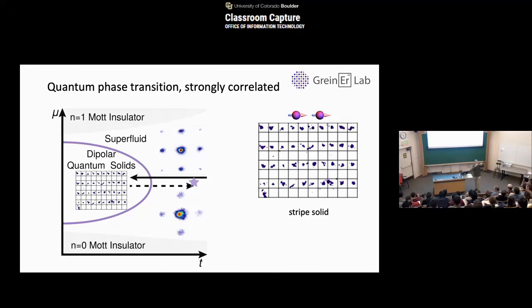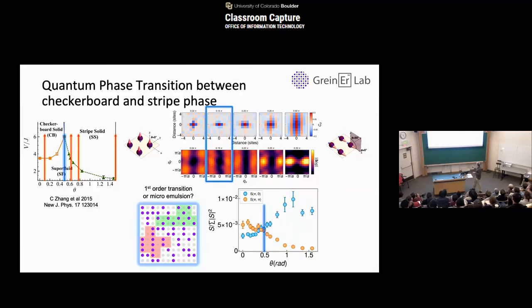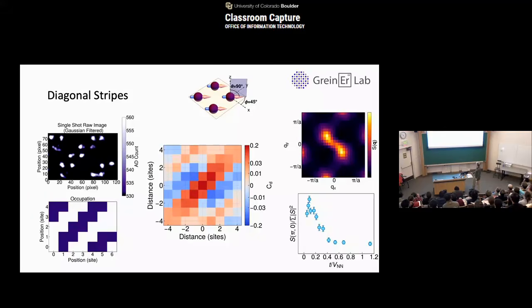because at first you can imagine you have macroscopic quantum fluctuations of stripes being here or here, and so there's a lot of interesting quantum mechanics happening on the way. In fact, we have started to study the first order phase transition here and found some evidence for microemulsion. We find at random places there is more checkerboard behavior, more stripe behavior, and this seems to be random and not pinned to any disorder and so on. But we just started to study this, so this is very preliminary.